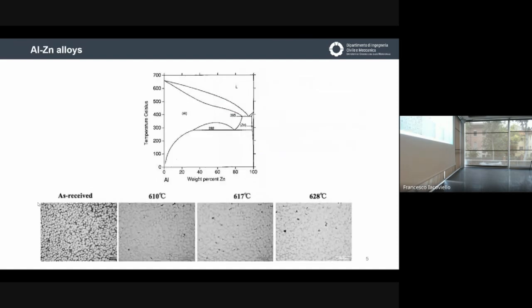What can I do? So this is the equilibrium diagram of aluminum and zinc. You can see that we have a very wide region of limit of solution, but an alloy with a concentration of zinc around 5% is used for other reasons. In terms of morphology of the structure, you can see the material as received, without any heat treatment. You can see the presence of the alpha phase, this one in white, and in black the beta phase that is rich in zinc. After the heat treatment it is homogenized, like this.